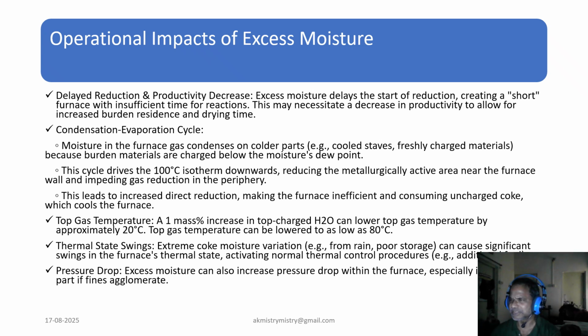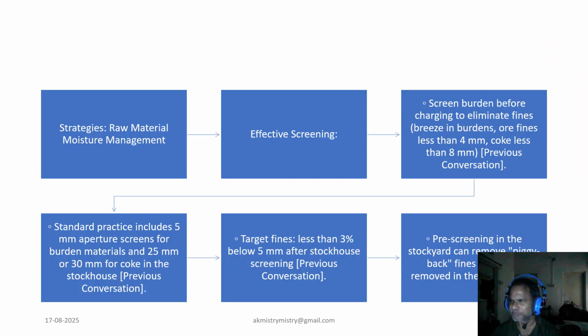Moisture in the furnace gas condenses on cooler parts like cooled staves or freshly charged material, because the burden materials are below the moisture dew point. This cycle critically drives the 100 degree centigrade isotherm downward, thereby reducing the metallurgically active area near the furnace wall and impeding gas reduction in the periphery. This leads to an increase in insufficient direct reduction, consuming uncharged coke and consequently cooling the furnace badly.